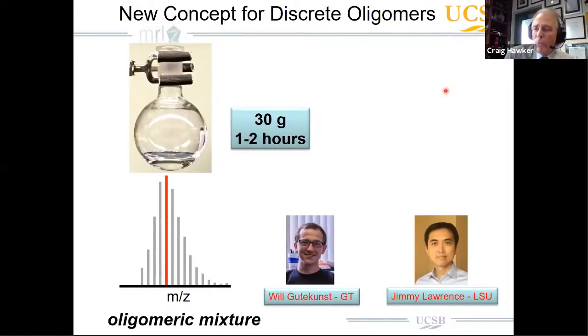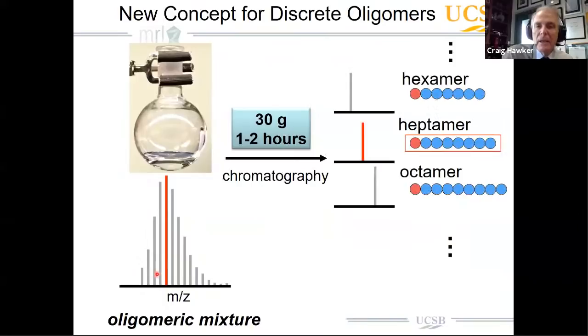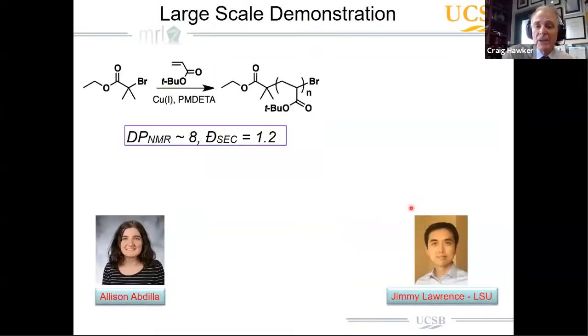They let the synthesis do a lot of the work for them in terms of controlling molecular weight, getting relatively low polydispersity, but being able to make large quantities of materials. And they coupled that with purification using an automated chromatography system. So in essence, it's easy to put on an ATRP reaction to make 30 grams of materials. It's about a 1 to 2 hour process. And as you can see here in this graphical representation, that's going to give you a set of oligomers. But you can then use chromatography, again, a couple of hours work, to hopefully, if you do the conditions correctly, take that oligomeric material and separate it into discrete hexamer, heptamer, octamer, and so on. And so that was the general strategy.